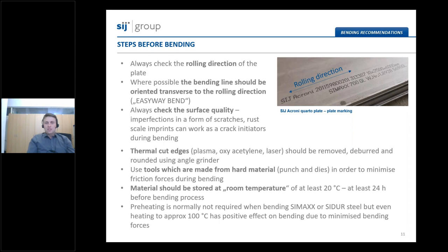Some of you might like to know if it is necessary to preheat the material prior to bending. Normally, it is not necessary or required. But if you preheat the area of bending to approximately 100 degrees C, this step will have a positive effect on bending, and almost no cracking is to be expected.